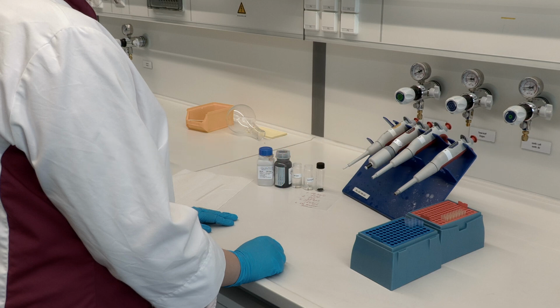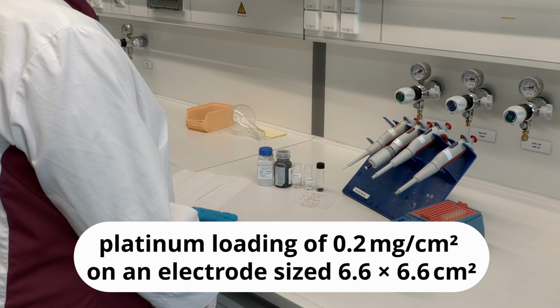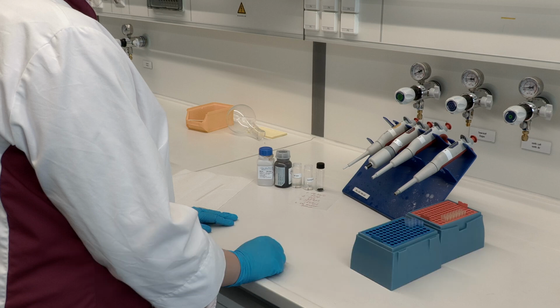To prepare an anode with a platinum loading of 0.2 mg per square centimeter on a 6.6 by 6.6 square centimeter electrode, you will need 80 mg of PT20 on C, 0.8 ml of deionized water, 1.6 ml of isopropanol, 0.8 ml of 5% Nafion dispersion.